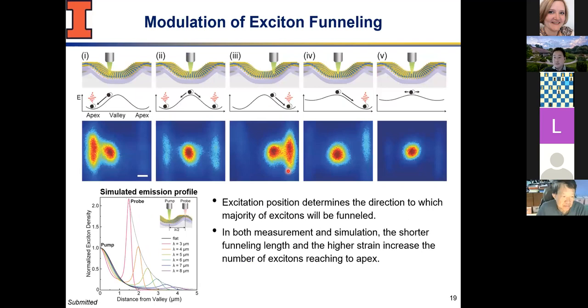Then you can start to do a more ambitious, more interesting experiment and try to correlate that with the energy diagram that I'm showing here. So this is my energy of, for example, the conduction band. That's another way to think of it, or band gap. At the apex, you have a lower energy. So if I offset my pumping just a little to the left-hand side, you have a barrier right here. So it's not supposed to go to the right. It can only go to the left. So if I pump here, you get very anisotropic emission. This component is truly drift. And of course, you have diffusion along the vertical line. If you put that in the center, then you get equal intensity left and right, so they can go to either left or right, and the same thing on the right-hand side.